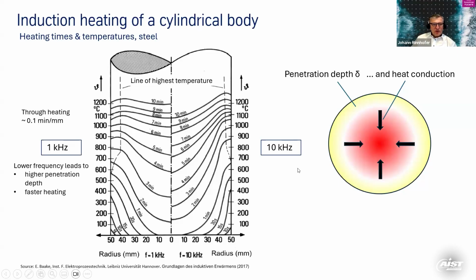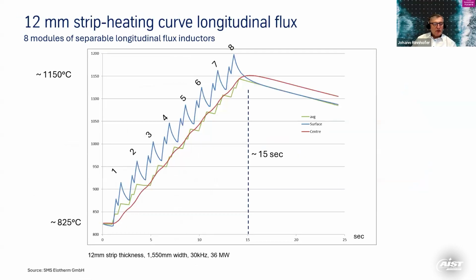You should not believe that the penetration depth and this inductive heating mechanism helps you with thick stock, because in the end you will have thermal conduction in the middle of the piece. So you have to wait until you have an equalization process as well for thick stock. So that's not as easy as it probably looks.